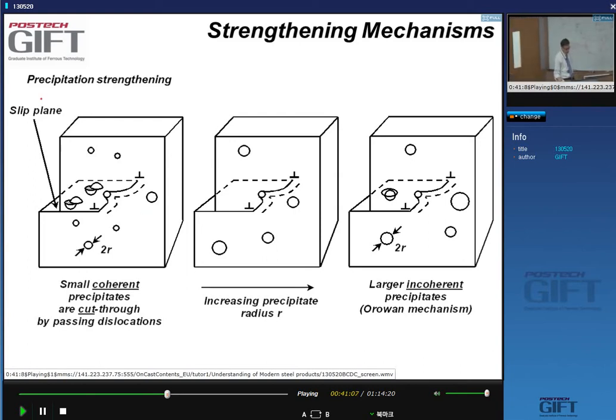Precipitation strengthening in steels. In principle, you can have particles inserted in the lattice, and these particles can interact with dislocations by being sheared by the dislocation. So the dislocation just passes through the particle. But in steels, we don't get this mechanism. Most of the time, we have larger incoherent precipitates, and we get what's called the Orowan bypassing mechanism, which gives us the strengthening.